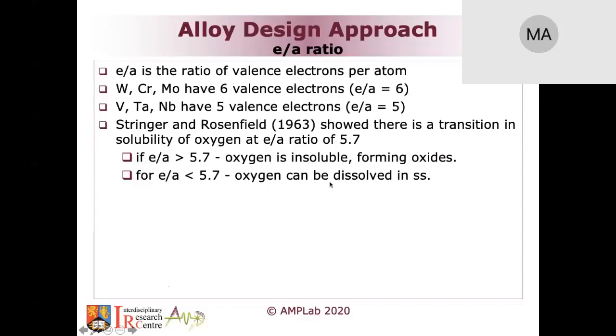In a sense, the idea is simple. If you forget about the numbers and how accurate they are, the message is that if you don't want the oxygen to be insoluble, then you just add one of these elements. So if you alloy, let's say, tungsten with tantalum, you might be able to get away with avoiding oxide formation. That can mean that the oxygen can be dissolved in solid solution to some extent.